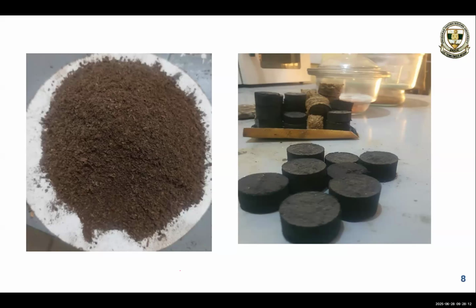Then we subject it to torrefaction, and at the end of the day, we come out with torrefied biomass. We also use another residue, which is cassava peel. Cassava peels, particularly those from bitter origin with high cyanide content, are no longer used for animal feed because of the high level of cyanide. When animals consume it, it becomes a problem that can even lead to their death. So that aspect of cassava processing is left underutilized. We say, okay, since this is the problem, we can selectively extract the starch from it and use it as a binder to produce our coal.